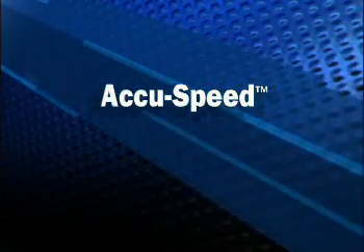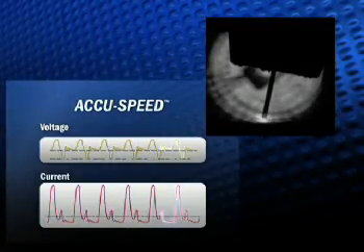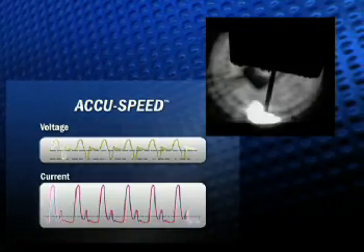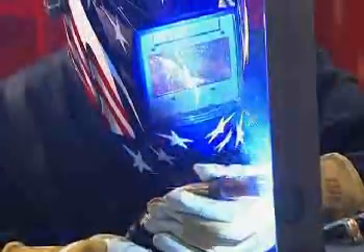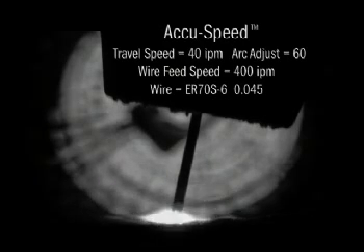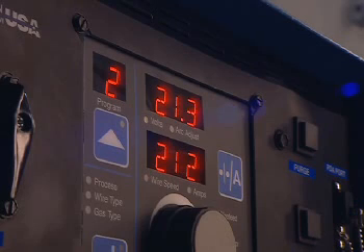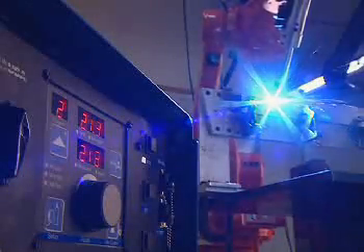AccuSpeed is a variation of the AccuPulse process. AccuSpeed uses the same CV adaptive scheme and waveform technology as the AccuPulse process. The AccuSpeed waveforms, however, were developed for the type of arcs needed in automotive frame welding applications. It can be used in manual applications when welding out of position, requiring a tight, fast-freezing arc. Tight, driving arcs can be directed into the joint and keep the arc stable at the high travel speeds used in automotive frame welding. In general, the AccuSpeed waveforms have a lower average voltage and amperage when compared to similar AccuPulse waveforms, reducing high heat input and warping.